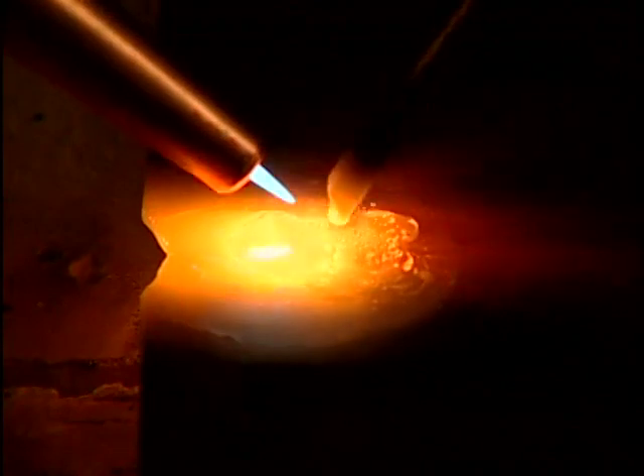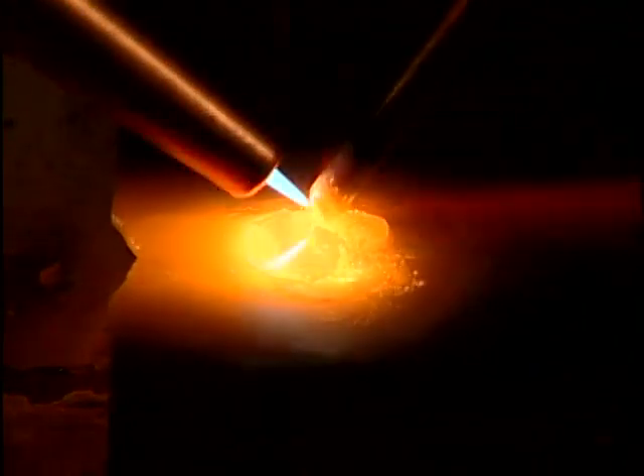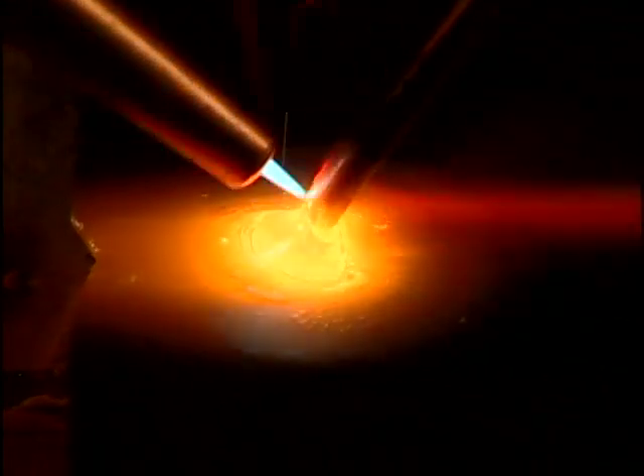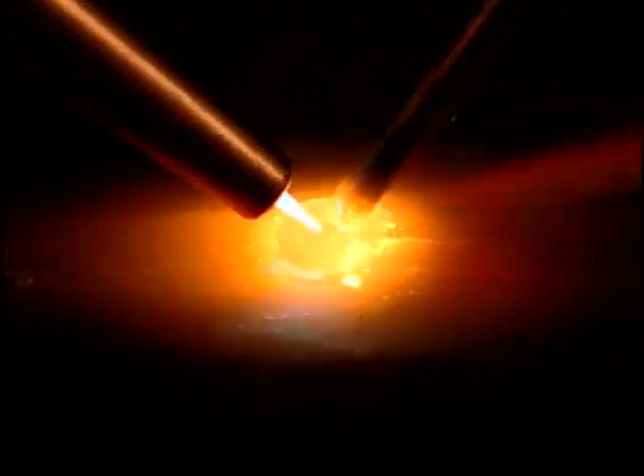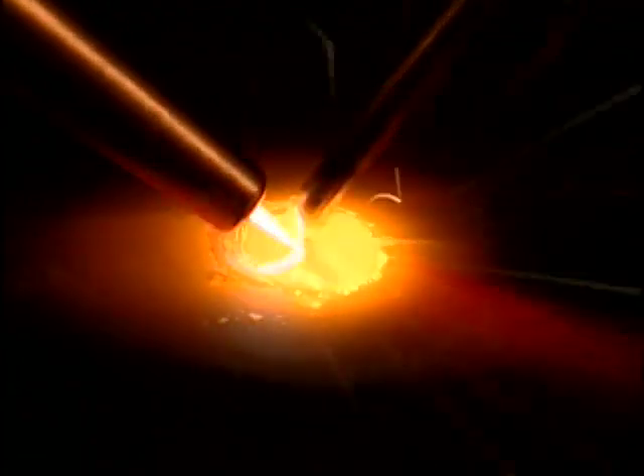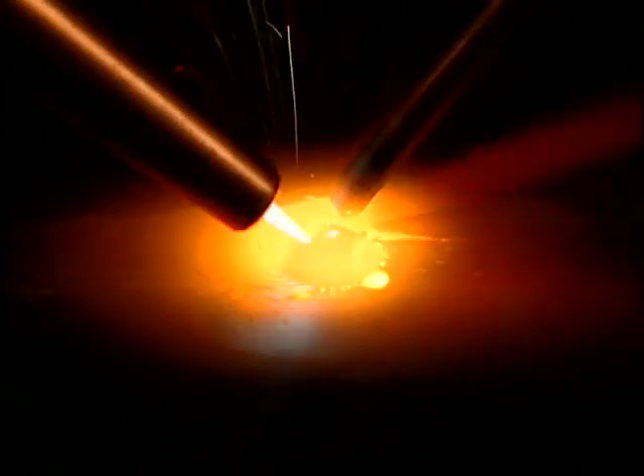Continue adding filler metal to the leading edge of the weld pool as the weld progresses along the joint. Surface tension on the molten weld metal will tend to pull it back away from the joint, leaving a gap in the center if the filler metal is not added to the molten pool quickly enough. If this occurs, add more filler metal until the weld bead unites into a single weld pool.